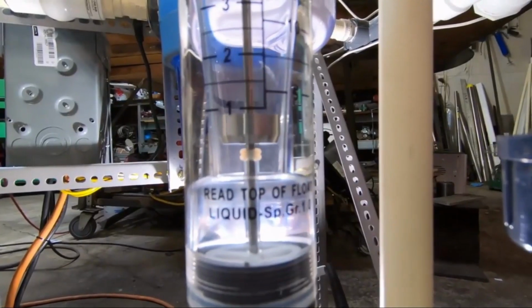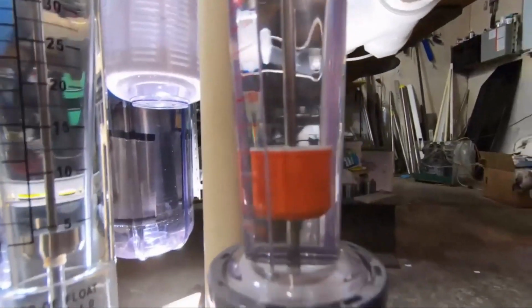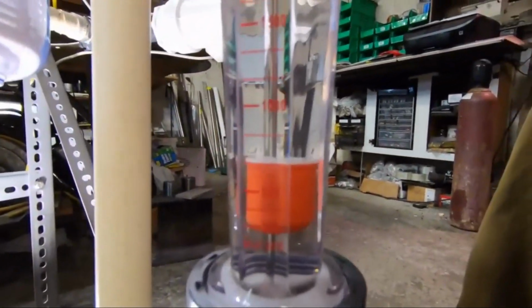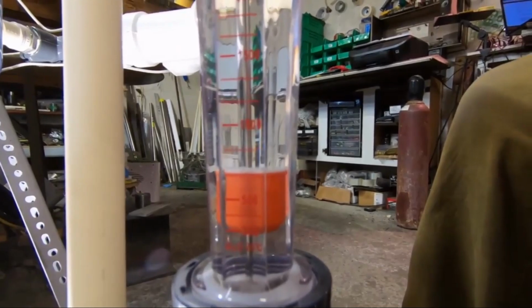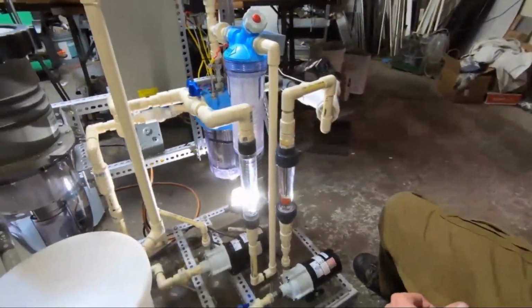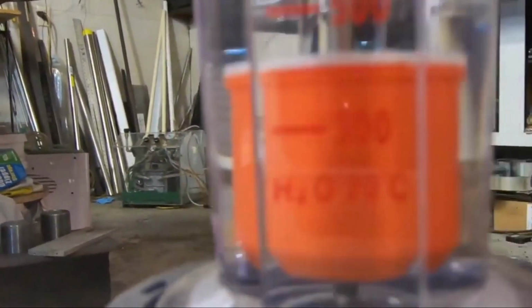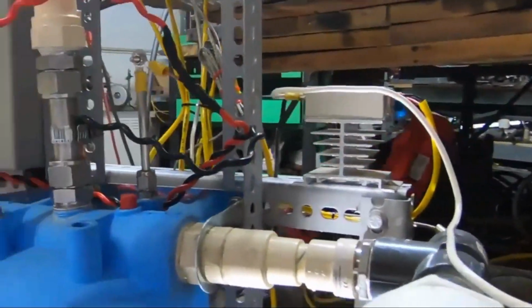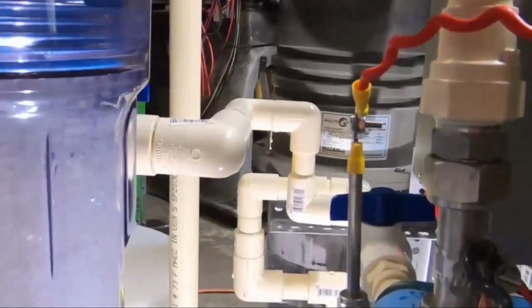6. Neutralization and pollution capture. After recovery, you're left with liquid streams that must be stabilized. This is where responsible plants separate themselves from backyard operations. Neutralization raises pH in a controlled way to precipitate dissolved metals into stable solids. Scrubbers capture acid mist. Filters capture fine particles. Water is treated before it leaves the site. If neutralization runs too fast or too far, the wrong compounds form and the loop breaks. Recovery without capture is contamination with paperwork.